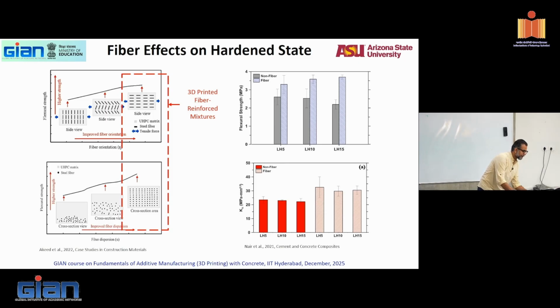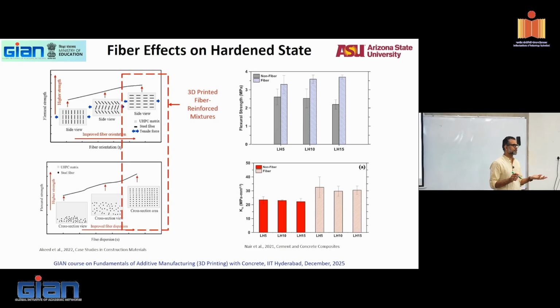Out of the fiber, which is good for tensile strength. Steel fibers, obviously, because steel has better tensile properties, it'll be better. If you want crack reduction, polypropylene is perhaps good. But aramid fibers are also very good, very stiff fibers, but they're much more expensive. But steel is perhaps the best and most commonly used.